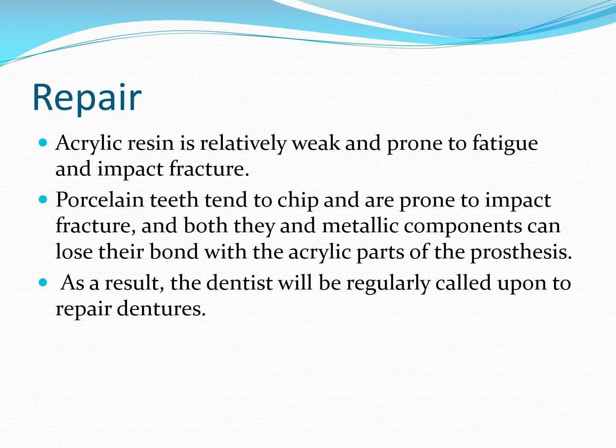When we use acrylic teeth, there is a union between the denture base and the acrylic teeth. But with porcelain teeth, while setting and processing, a void or gap can form between the acrylic and the porcelain tooth. This void cannot tolerate the extra pressure, and there is no chemical union, only mechanical union.